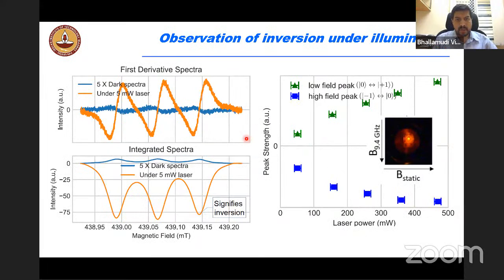And so we still don't have a maser as yet in our lab, but what we have done is the first step towards it, an important step, which is showing the inversion of the population. And so we have been able to create this inversion of the population. This is work done in a conventional EPR cavity. So these are standard EPR measurements, but now we are doing them while applying the laser and without the laser, which is this dark spectrum here. And this is 5 times multiplied already.